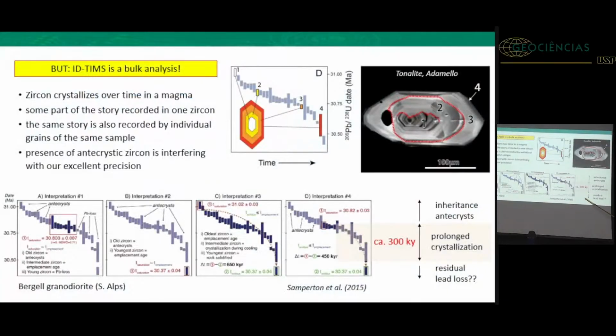But we'll probably come up, by analyzing several samples, with a load of antecrysts which crystallized earlier and got transported into a higher crustal level. Then we probably have some prolonged crystallization, maybe of 300,000 years, and then we may have some residual lead loss, possibly. And this 300,000 years of prolonged crystallization is a value which comes up again and again, also in modern systems, as the maximum period of time you manage to keep zircon crystallizing and the melt system alive. So in so-called hot zircon crystallization models.